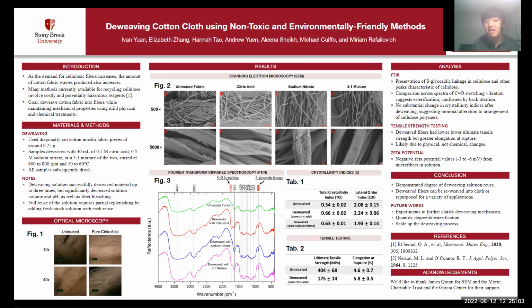Tensile tests, seen in table 2, revealed that compared to untreated fibers, citric acid deweaved fibers have a lower ultimate tensile strength, but a greater elongation at rupture. This decrease in strength is likely due to physical rather than chemical changes.